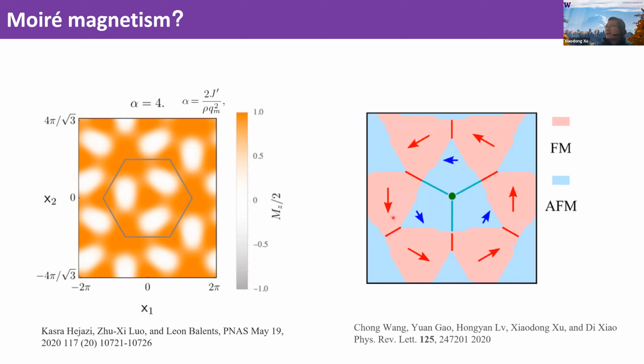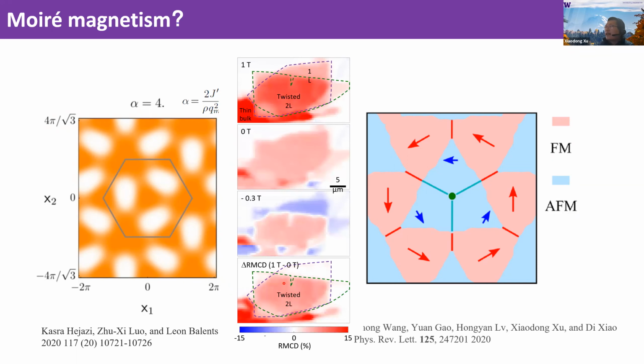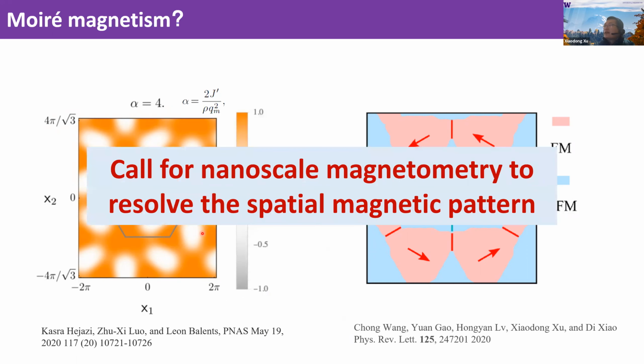such a structure. But in our measurements, look at what I have, nothing looks like what the theory predicts. The main reason is that we're doing optical measurements, and the laser spot size is limited by the diffraction limit on the order of 1 micron, but the domain is on the order of 100 nanometer scale. So we don't have enough spatial resolution to tell the magnetic patterns. So we have to find a technique able to resolve these.